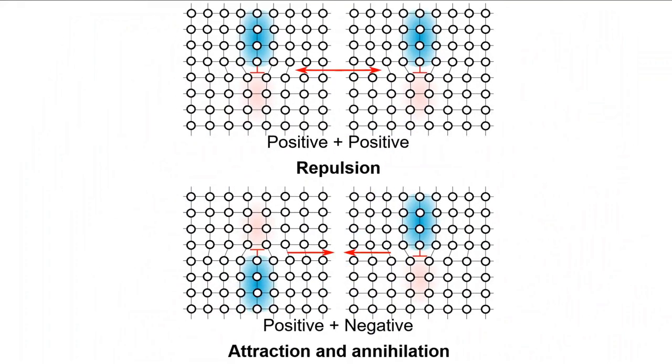If you recall, both edge and screw dislocations can interact when they are brought into each other's influence on the basis of their strain fields. Here I'm showing an edge dislocation as they're easier to depict, but the same thing happens for screw and mixed dislocations. If there are dislocations with opposite sign that interact, then both dislocations will be cancelled.